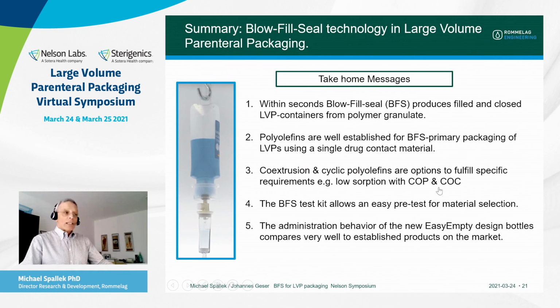Let me summarize. Blow fill and seal technology in large volume parenteral packaging. In seconds, blow fill and seal produces filled containers, tightly closed, with machines that are very compact in size. Material-wise, we do prefer the polyolefins, and this is then the single drug contact material. Extractables and thereby leachables are not of a high concern.